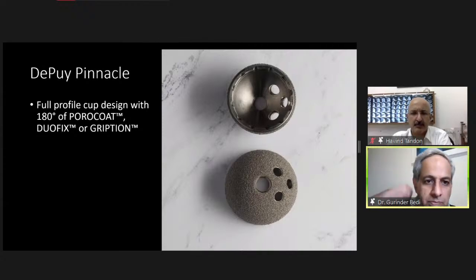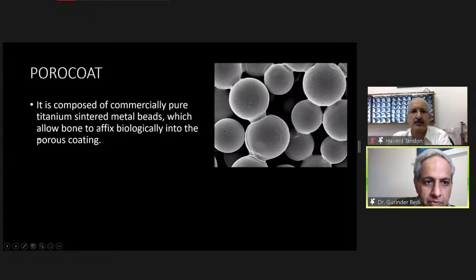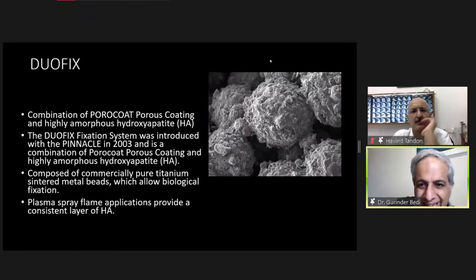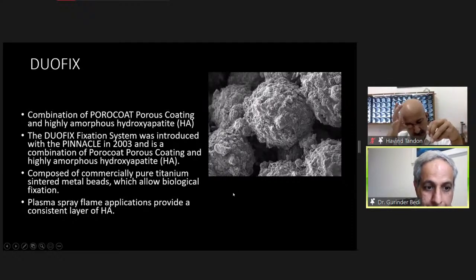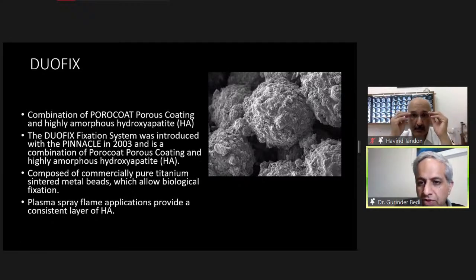What about DePuy? DePuy has been making the Pinnacle cup, which I think a lot of people are aware of. It basically comes with three options: Porocoat, Gription, and Duofix. Pro Coat was just a sintered titanium, a smoothened out piece which you put on it, which they've been using for a very long time. Then the next step was you do the Pro Coat and then you throw hydroxyapatite on it. And you still produce a lot of roughening and porosity on it, but it actually improves the whole thing much better. So it's a plasma spray application.